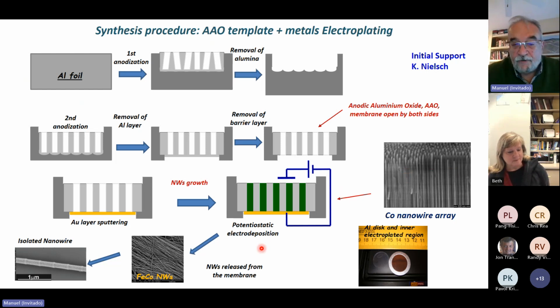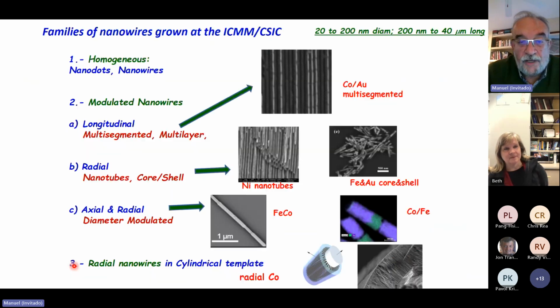But in the last years, we have been focusing on the study of individual nanowires, and I wanted to show you our results. We have the nanowires after release from the membrane. The alumina membrane can be removed by a chemical process, and the same way we can eliminate the aluminium. So we get the isolated nanowires, and then after a tedious process, we have to separate the nanowires by centrifugation several times. It takes time, until finally we get an individual isolated nanowire.